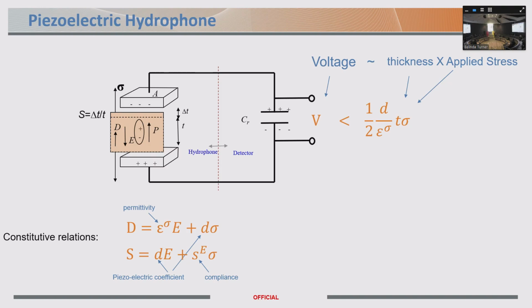And the important point to see here is that you have something called a piezoelectric coupling, which means that the stress and the electric displacement, i.e. the charge, are coupled by this material parameter called the piezoelectric coefficient. And if you work out the voltage that's generated there, the maximum possible voltage that you get is related to this piezoelectric coupling coefficient and the electric permittivity for a given stress.